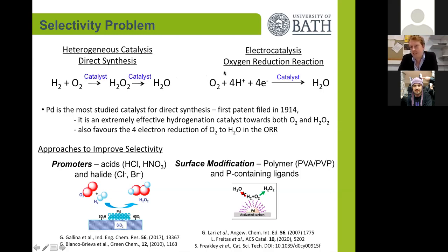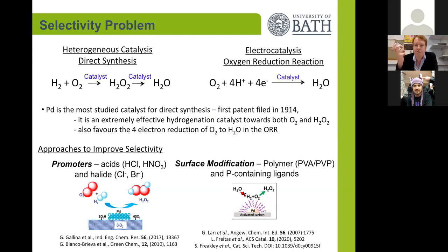In both these systems, palladium is the most studied catalyst, where the first patent was granted over 100 years ago for the direct synthesis. However, palladium, as you will know, is an extremely effective hydrogenation catalyst towards both oxygen and hydrogen peroxide. And palladium also favors the four-electron reduction of oxygen straight to water under acidic conditions.